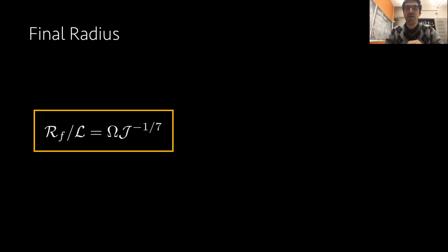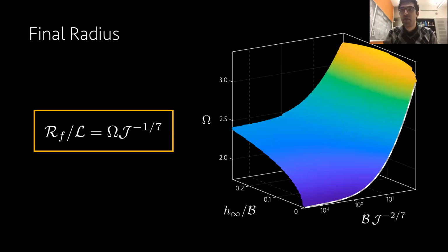Okay, so I try to avoid all the algebra and give you the final results. I can basically say that my final radius follows this scaling law that I showed you before, and my prefactor is a function of some of those parameters, namely H infinity and Bond number. If you do a lot of those asymptotic solutions, you can put all the results in such a 3D curve. What it shows is that as your H infinity, your pre-wetted film thickness, goes bigger, your omega goes bigger, and as your Bond number goes bigger, again, your omega increases. So all you need to know is basically this is your scaling law.